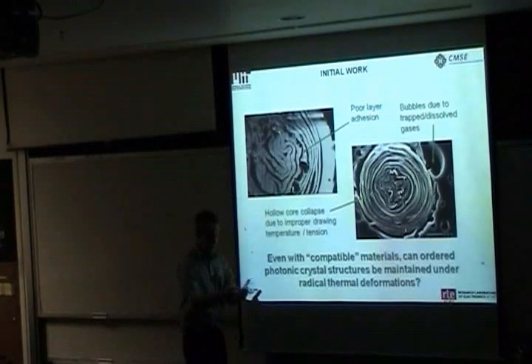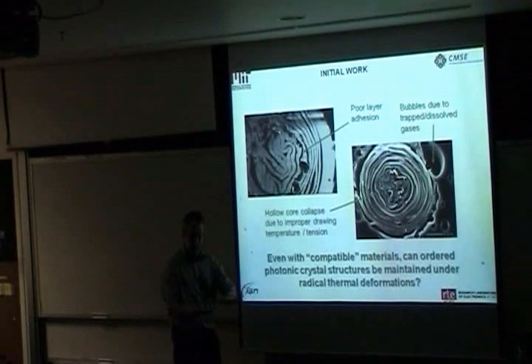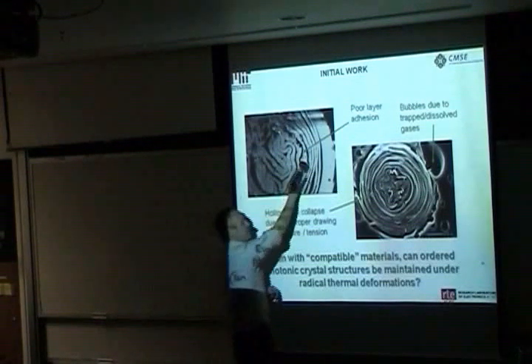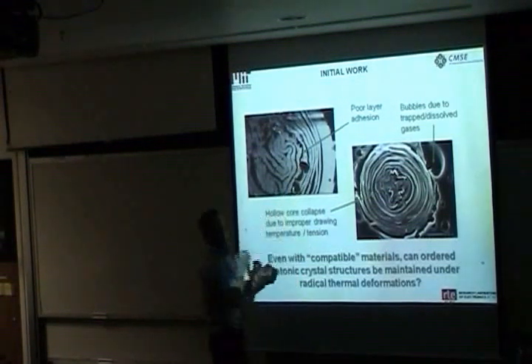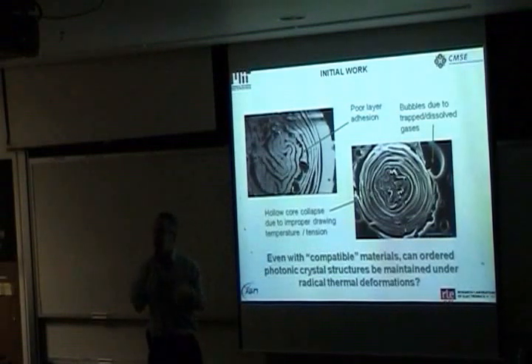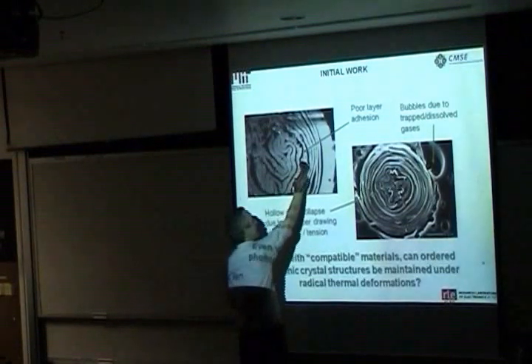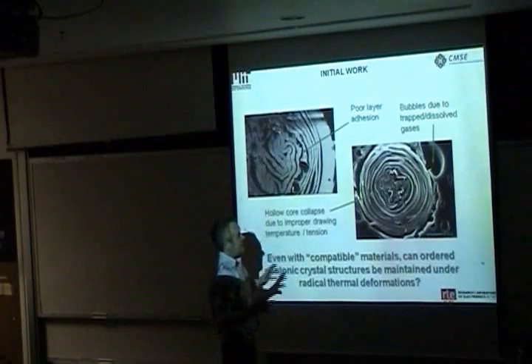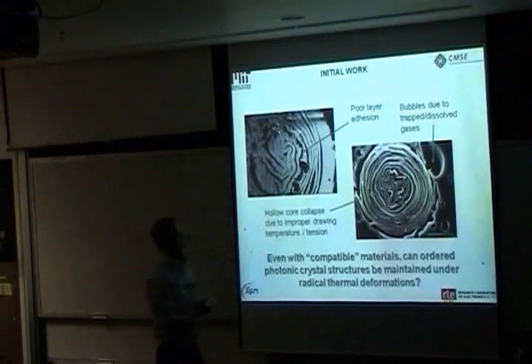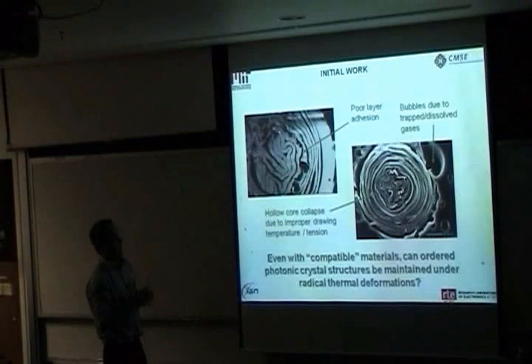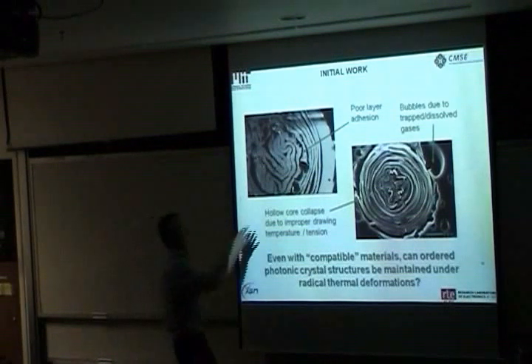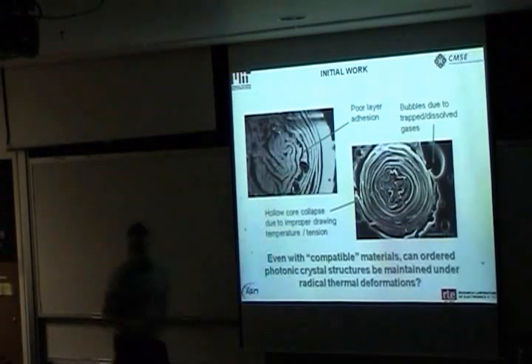Another thing is we actually started with taking polymer sheets and coating them with this semiconductor glass and then wrapping those around. Well, as you wrap them around and then draw this thing, there's lots of little gases that get trapped, and once you heat them up in the draw tower, they like to bubble up and form these very nice little inclusions here. But the take-home message from all of this was, at least there were some good things going on. For example, the fact that the materials appear to be flowing at the same temperature, which at the time we thought was nice.